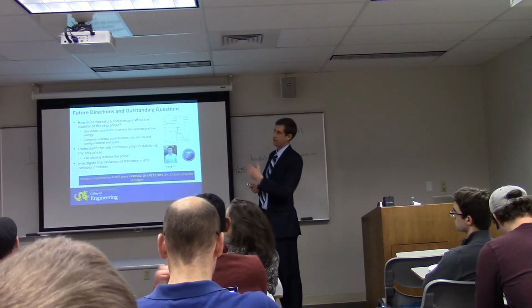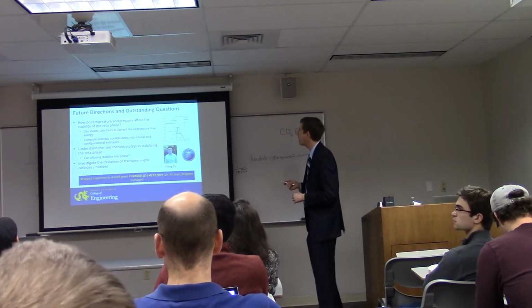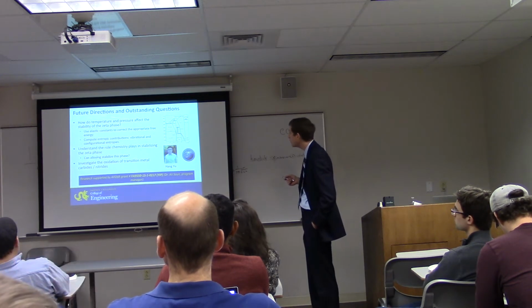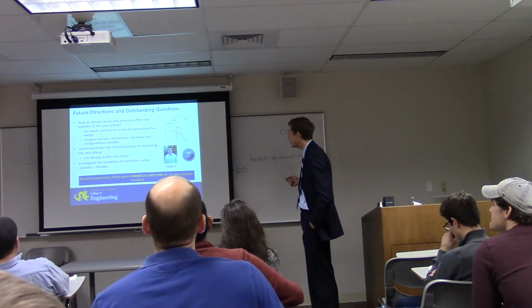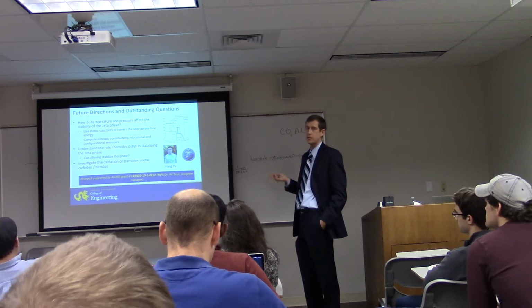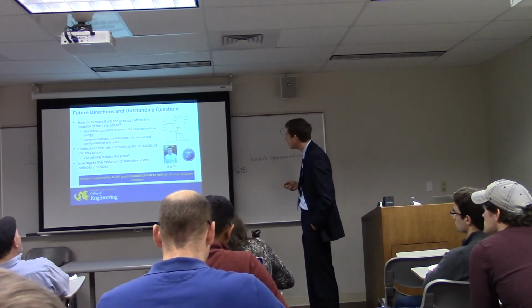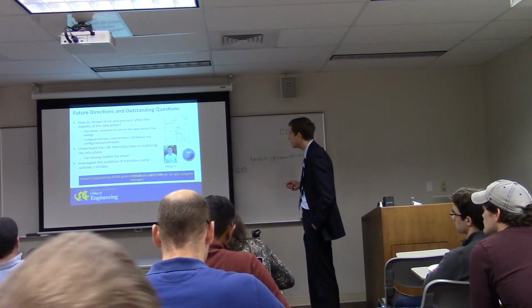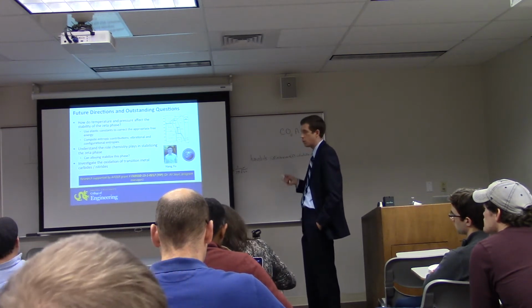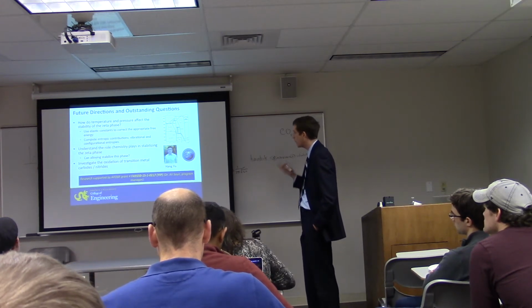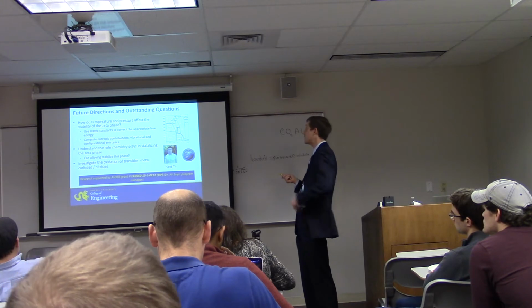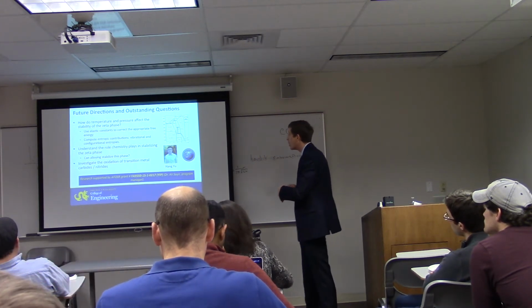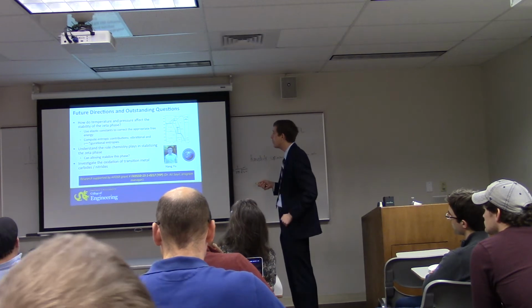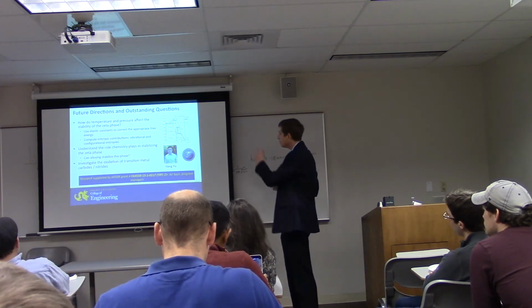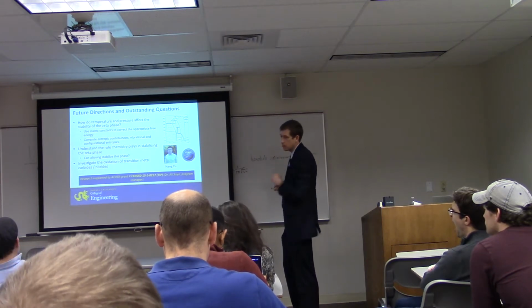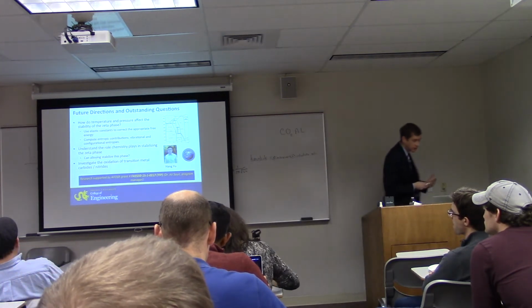I was asked, and I see that I'm going to exceed my time, I apologize, to talk about future directions. In this work, one of the things we're working on right now is that we dealt with everything at 0 K. DFT is limited in that sense. There have been a lot of questions about how temperature and pressure affect the stability of the zeta phase. We're working on that right now. We get at that by computing elastic constants, which can give us pressure dependence. It can also give us corrections to the free energy. And we can also compute entropic contributions in terms of the configurational entropy, so that we can correct free energies to finite temperature.